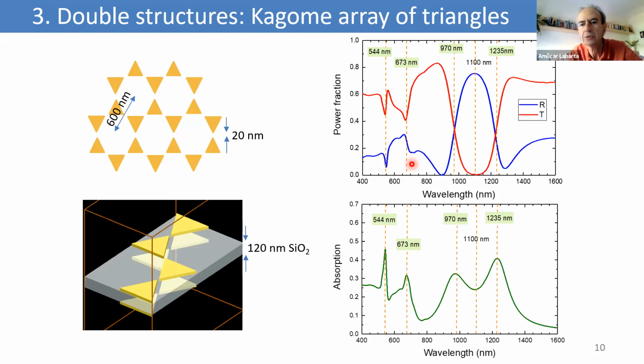The absorption shows peaks which are pretty high. Okay. And you can also see two broad peaks related to near-field interactions. Here we have two near-field interactions because we have the common near-field interactions through the gaps, but we also have near-field interactions between the facing triangles.